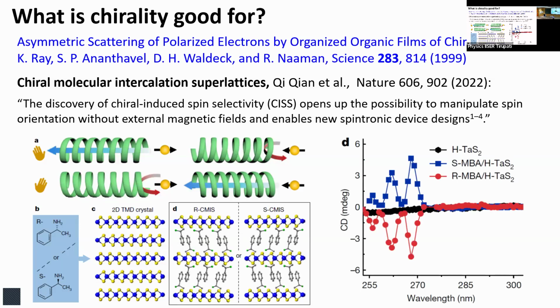Once you do the absorption experiment with right circularly polarized light, and the other time with left circularly polarized light, because right and left polarized light absorb differently depending on whether they're in sync or out of sync with the chirality of the molecule. So immediately the difference between the two tells you: if it is not a chiral system, both right and left circularly polarized light absorption will be identical, and you get zero in the difference.